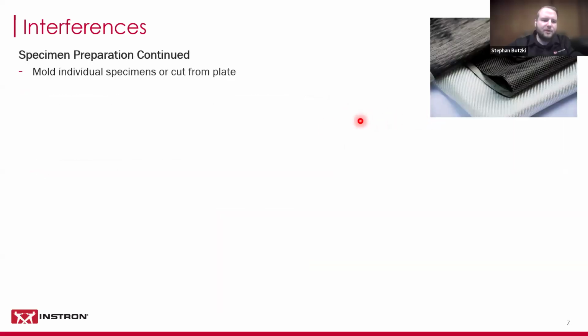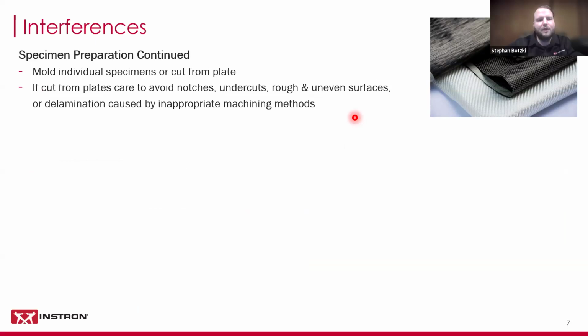If you make specimens, you should consider molding them individually, or if you have to, you will cut them from a plate. And if you cut them from a plate, you need to make sure that you avoid any kind of notches or undercuts or rough and uneven surfaces. Or you could also have delaminations, which could be caused by any kind of inappropriate machining methods. So this is when you're actually milling the composites. So be really careful with that.